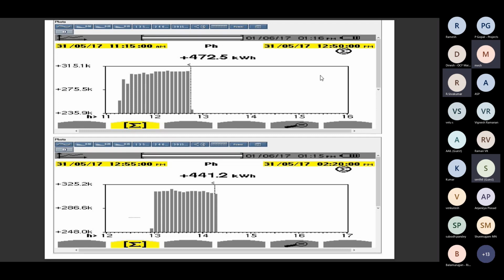After the new sintering practices and the raw material charge pattern, the same foundry achieved nearly 441.2 units. So for almost 550 to 580 kgs of liquid metal, they are able to reduce nearly 30 units per heat, due to proper sizing of the raw material charging sequence and also the best practices adopted in the sintering practices. Next one.